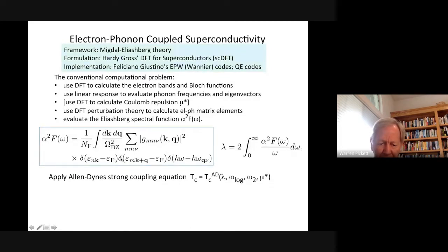But you have 2 delta functions here because the initial electron has to be on the Fermi surface. And after scattering, it also has to be on the Fermi surface. And then this is frequency resolved. So all of these phonon frequencies that come in here and the branch index, those are projected on h bar omega. And then you plot this as a function of omega. F of omega is just the phonon density of states, and alpha squared is the mean square coupling at frequency omega that comes in here. So this is a substantial calculation. The phonon coupling strength, lambda, is given in terms of this function simply by the integral over this function times 1 over omega. So it's the inverse frequency moment of alpha squared F.